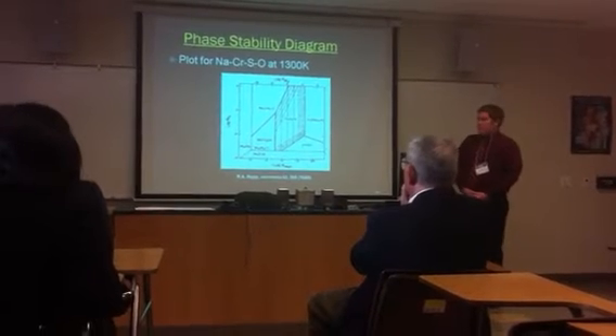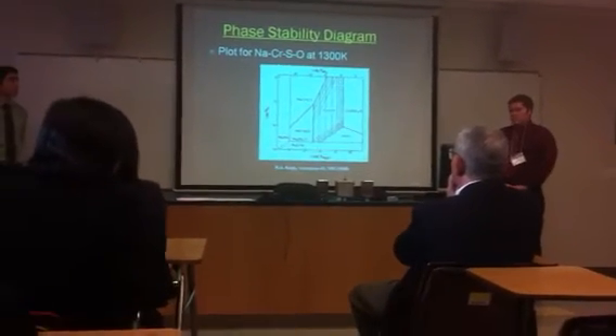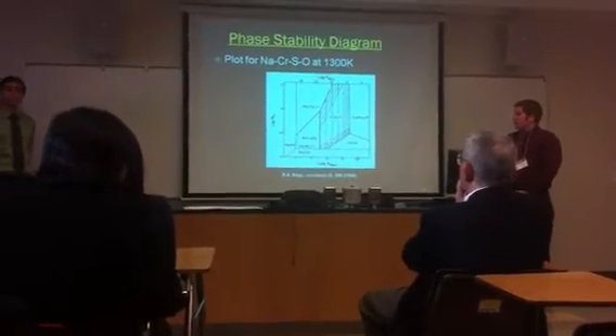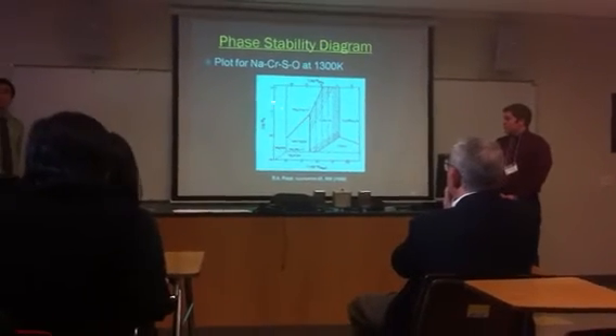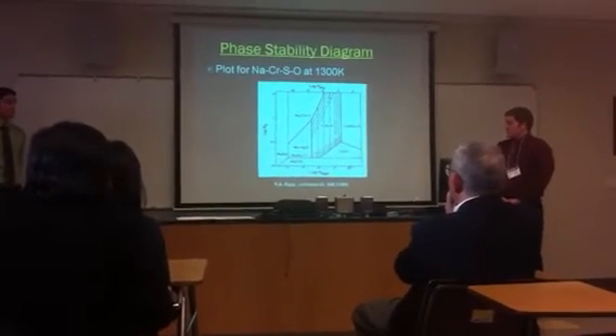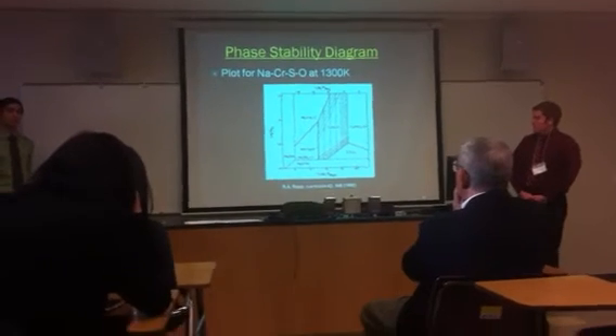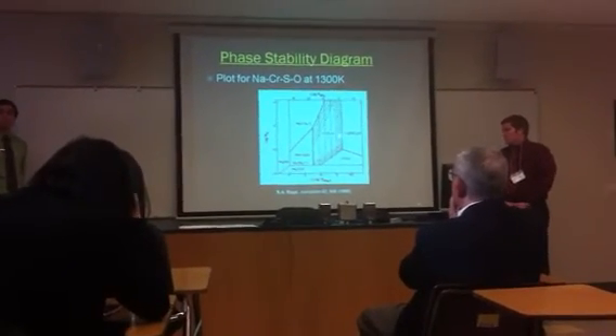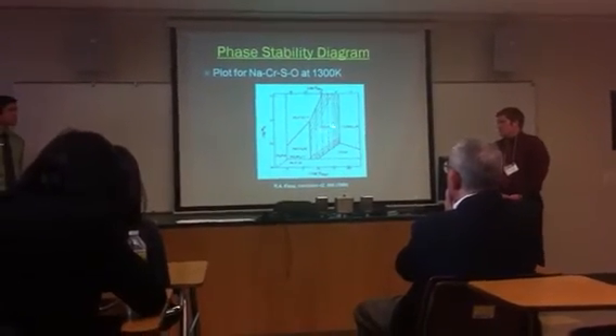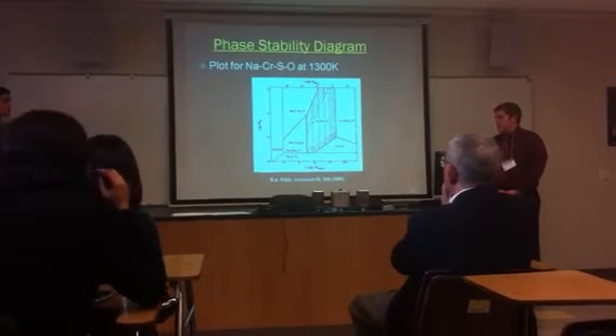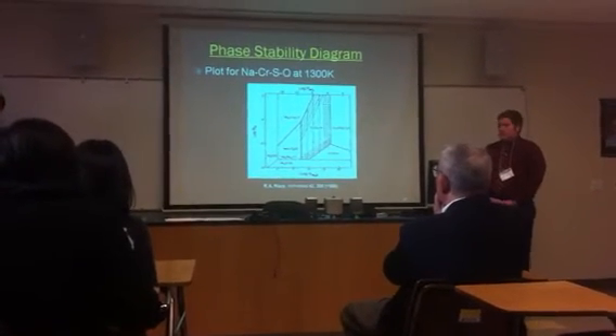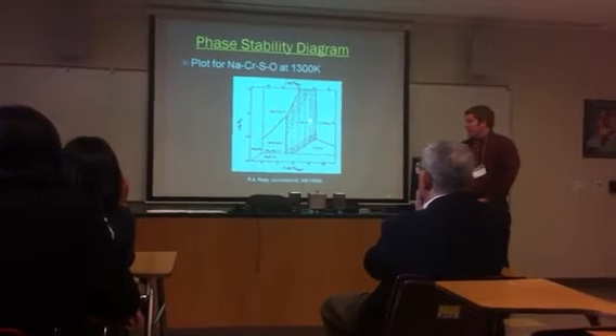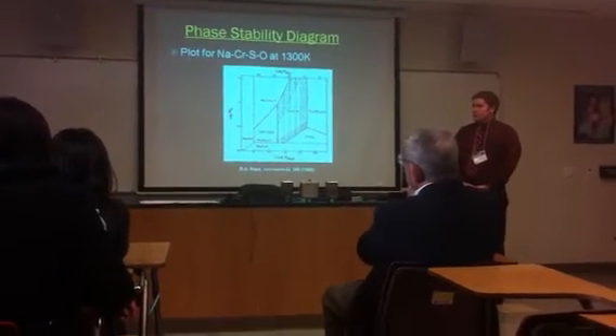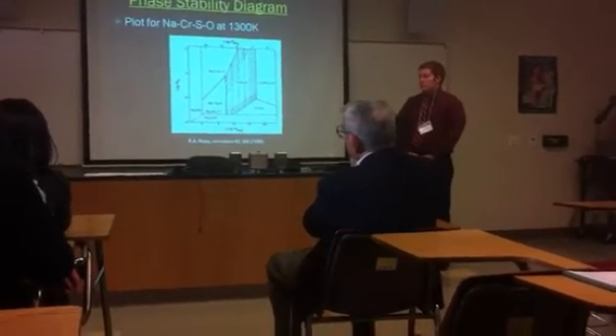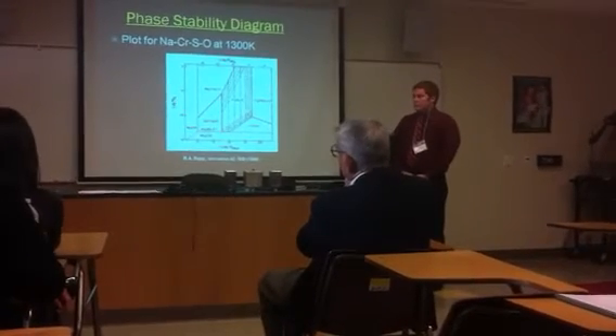And here is our phase stability diagram for a sodium, chromium, sulfur, and oxygen system. Once again, we have the log of PO2, the negative log of activity of sodium oxide. And right here is the oxide that is formed with the chromium alloying content in our nickel substrate. This chromium oxide is what we are looking to form to combat this hot corrosion phenomenon.